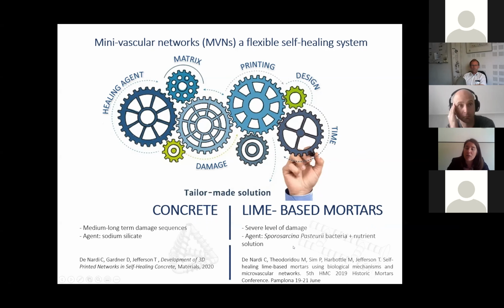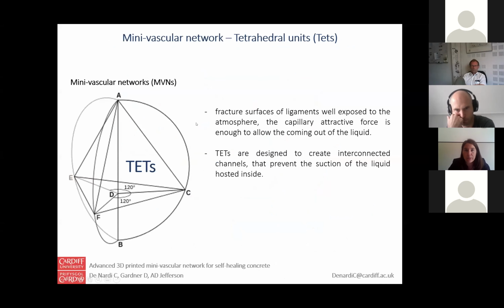You can find some details here already published. And interestingly, when the matrix is made of lime-based mortar, we have studied a severe level of damage, and here the healing agent is a solution of Sporosarcina pasteurii bacteria, dispersed in the matrix, while the nutrient solution was stored inside the mini-vascular networks. And here you can find very first results in the 5th Historic Mortar Conference proceedings.